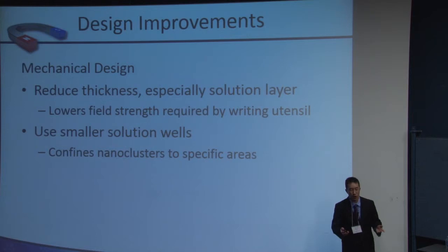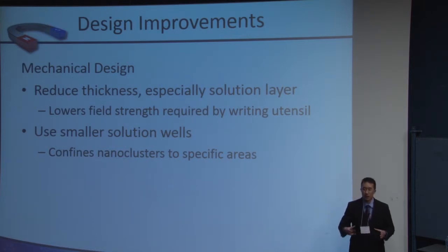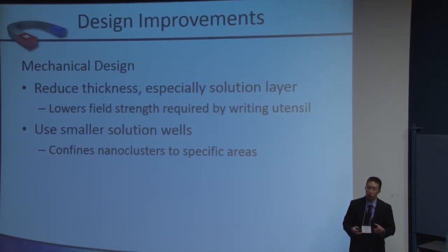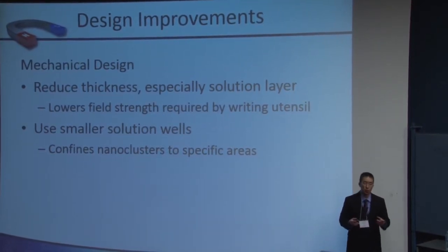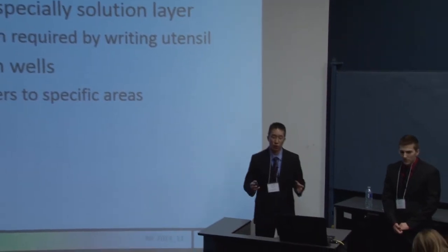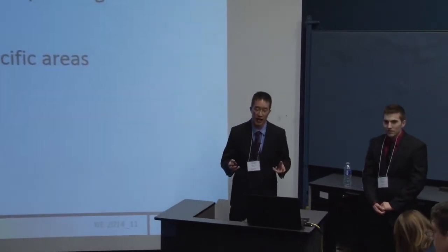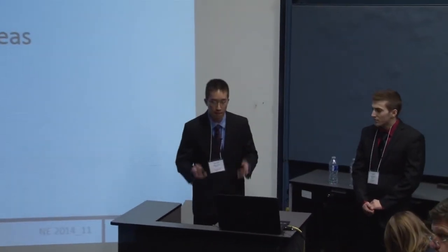One of the issues with our second prototype, which did not feature wells, was that the nanoparticles could easily be drawn to points that have been magnetized, and thus it will distort the overall image over time due to the fact that the concentration of nanoclusters at that area will be much higher.